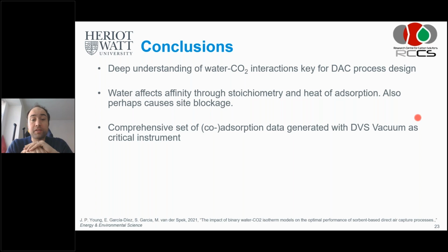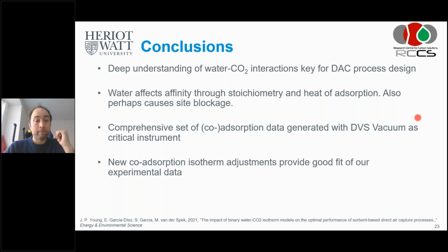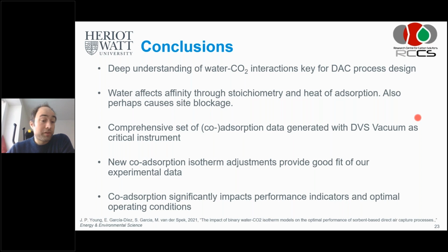So we generated a comprehensive set of co-adsorption data with the DVS Vacuum as a critical instrument. There aren't many other instruments that have that capability. We have provided new co-adsorption isotherm models, and they provide a good fit for our experimental data. And we have seen that co-adsorption significantly impacts the performance indicators and optimal operating conditions of a direct air capture process. So again, this is really key to understanding the performance of a real DAC process. I have some backup slides if anybody has questions, but for the moment, I wanted to leave it with this.